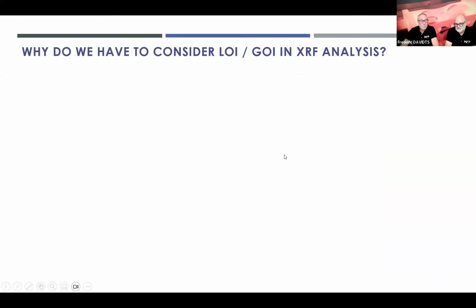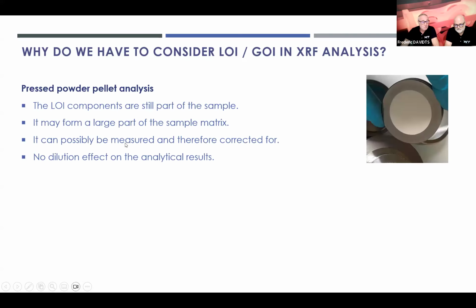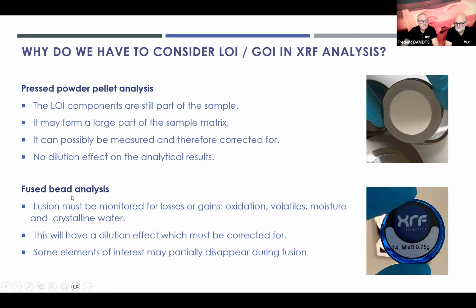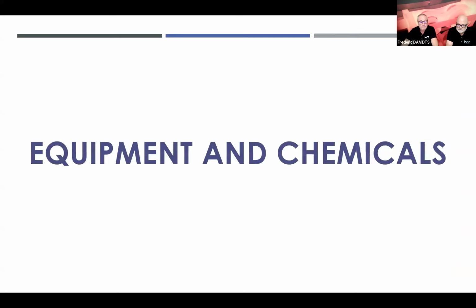But the question is also, well, what do we do with loss on ignition or maybe gain on ignition in XRF analysis related to fused beads, related to pressed pellets, which will, I repeat, in November be another topic we will talk about. So when we talk about the pressed pellet sample, we know that the LOI and all the other components are still in the sample. They are part of it. In the case of a fused bead analysis, we will lose these volatiles. The loss on ignition will be lost when we heat the sample up. So we must take this into account in our calculations, or maybe introduce it in the software of the spectrometer.